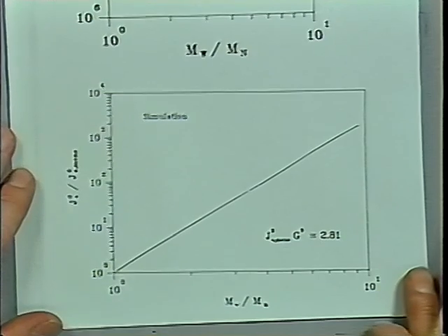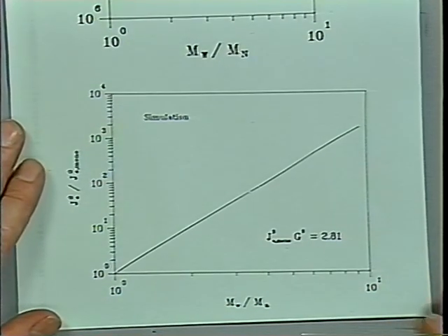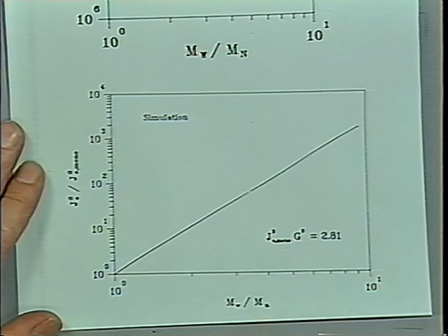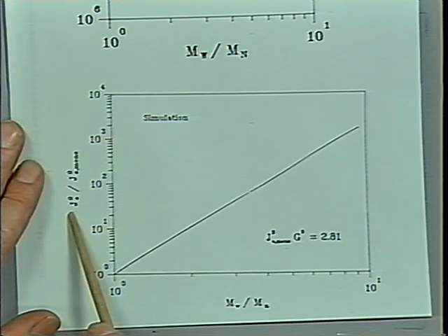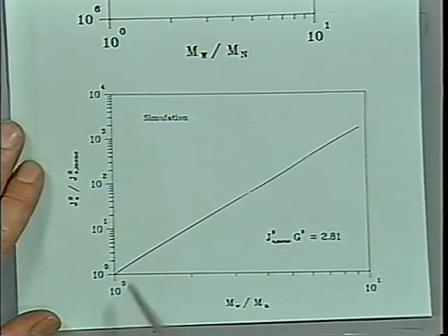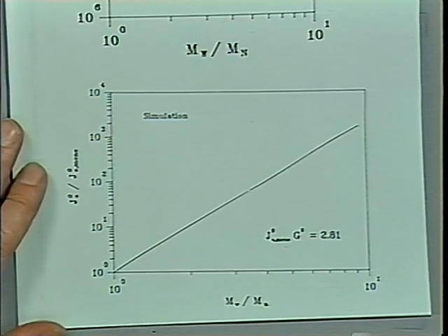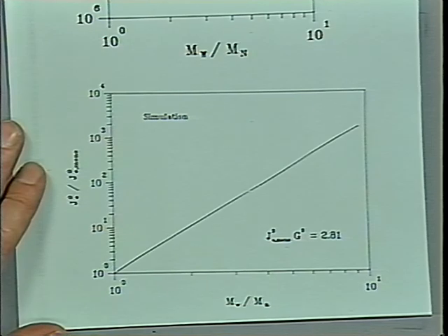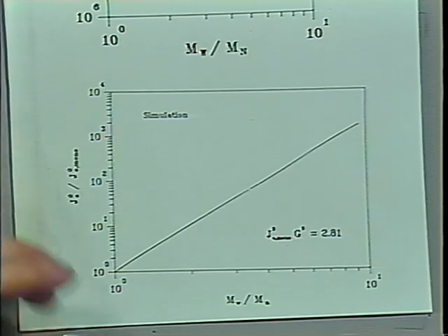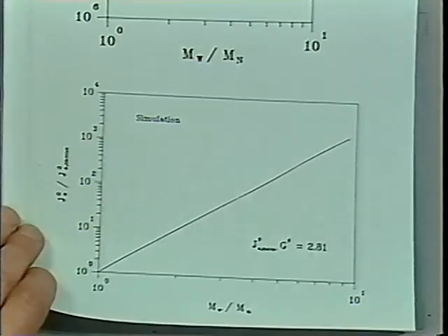The zero shear compliance is another sensitive measure of the broadening. If you now plot again MW over Mn and compare the zero shear compliance with its ideal value of the monodisperse, then you see a power law behavior. It increases in a power law. It's a very strong dependence of this compliance on the broadening of the distribution. So if you look at polymer systems of different widths of the molecular weight distribution, then the zero shear compliance is a good quantity to look at, and that's very well known.